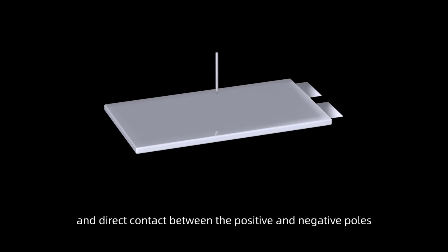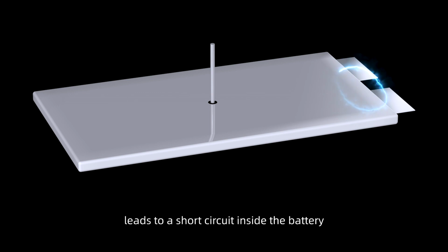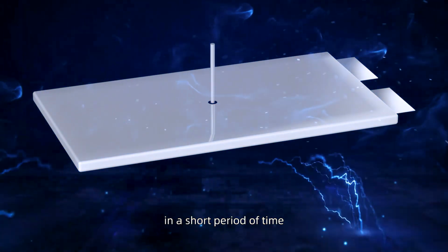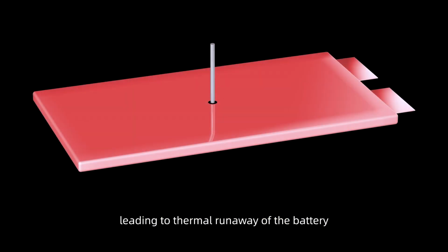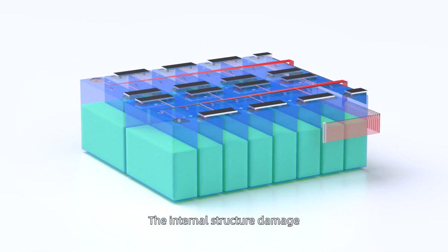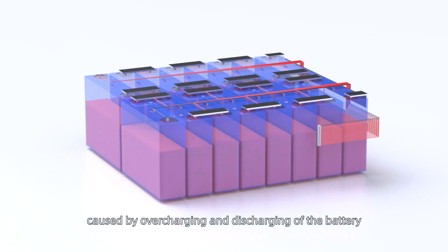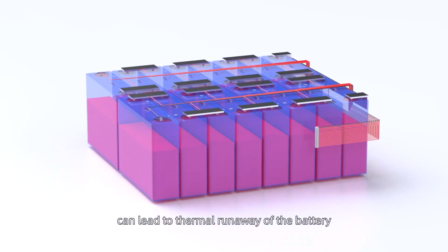Second, external damage caused the battery separator to be penetrated. Direct contact between the positive and negative poles leads to a short circuit inside the battery, releasing a large amount of electrical energy in a short period of time, leading to a thermal runaway of the battery. Third, the internal structure damage caused by overcharging or over-discharging of the battery can lead to thermal runaway of the battery.